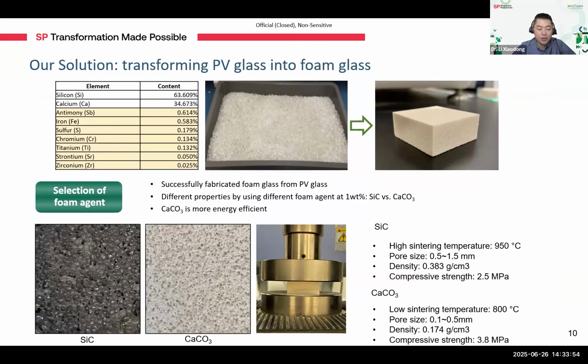Our solution is to transform the glass waste into a foam glass panel, a lightweight, porous, and robust material with excellent thermal insulation properties. We have successfully converted the waste glass into foam glass and focused on optimizing its performance. The insulation quality of the foam glass depends heavily on its composition and the processing conditions. We tested different foam agents and carefully tuned the manufacturing parameters. The key evaluation factors are pore structure and size, pore uniformity, and material density.